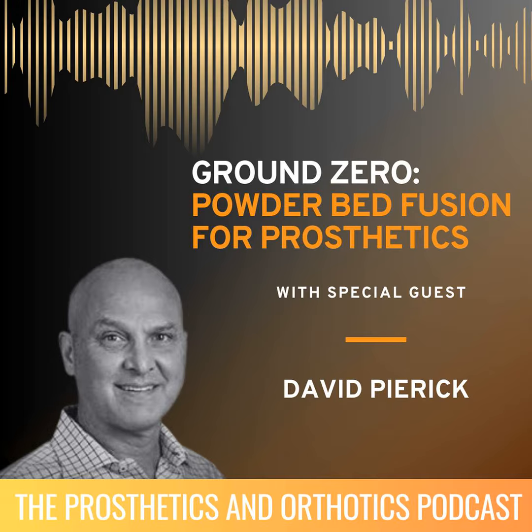And so my encouragement to people is really, when you're designing these things, you want them to flow very nicely. Like what David said, is no hard edges, no 90-degree turns with an edge. You always want to radius. And then if you need some areas that are thicker or thinner, the tendency is just to throw a rib or some sort of corrugation there. But what we found is that if you do that and you don't transition that corrugation to the actual surface itself, that also can present stress riser challenges.